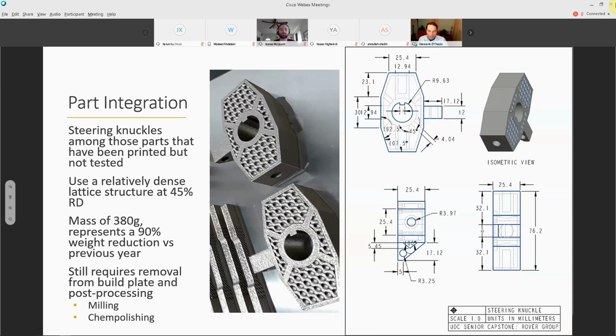So from there, we were taking our data to design and print our steering knuckles. So they've been printed, not yet tested. In fact, they're still on the build plate exactly as they look right now. We used a relatively dense lattice structure at 45% relative density, so kind of cutting the middle between two upper ends. We had a really large reduction in mass compared to our previous Rover's steering knuckle design. So at 380 grams, we had a 90% reduction in weight.